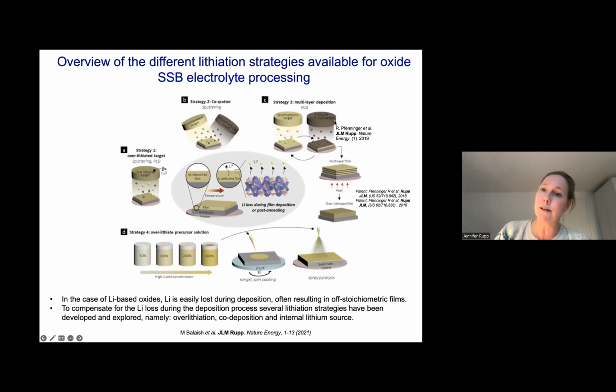And then we introduced a second target that we made, which is lithium nitride, which is very close to the laser energy and the wavelengths at which we ablate with our lasers and material. And if you ablate sequentially, like a multi-layer from both compounds, you can use the lithium nitride as an internal lithiation source by later annealing the film at about 650 degrees C. Then the lithium nitride decomposes, the nitrogen goes out, and the lithium gets stuck in the lithium garnet structure. And then you get a very over-lithiated, very finely lithium stoichiometry controlled material.